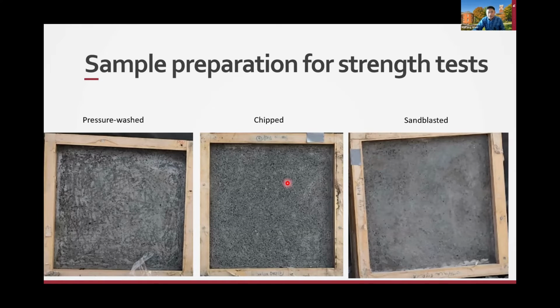the strength test. For the strength test, which is different from the butterfly test, you prepare these panels of concrete, and still do the surface preparation using the pressure washing method to make the surface rougher, hopefully increasing the bond, or the chipping method, or the sandblasting method. So all the intent is to make the surface a little bit rougher, so hopefully the bond is higher.